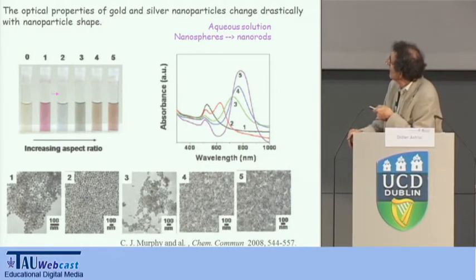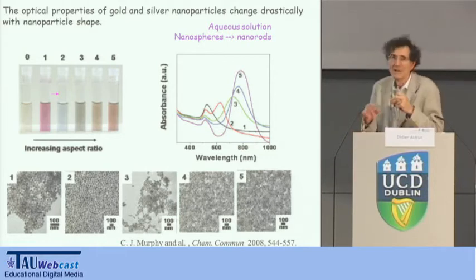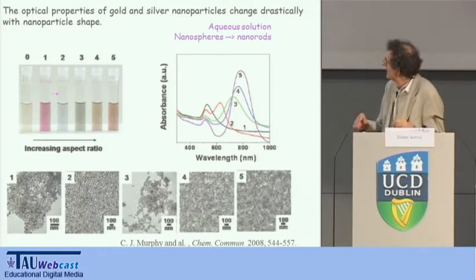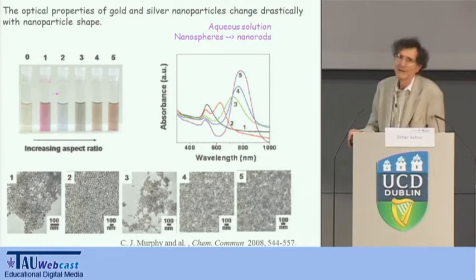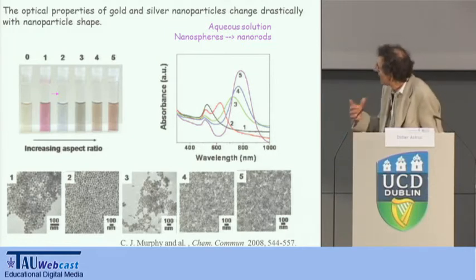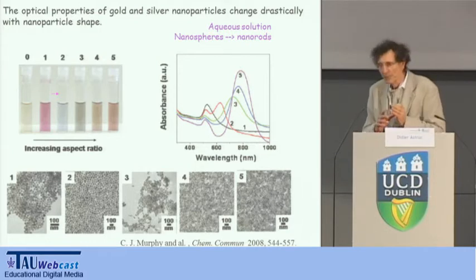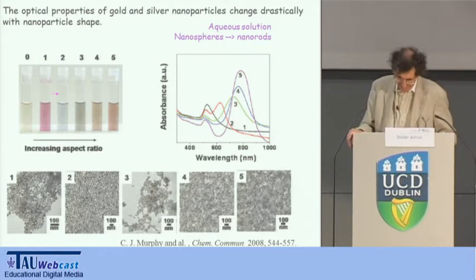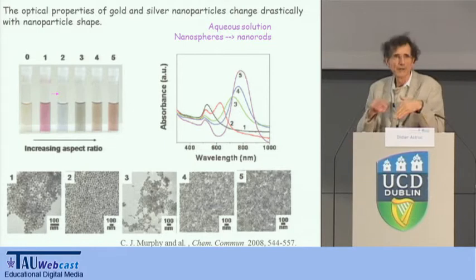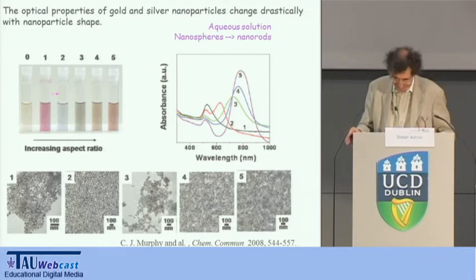And you can see here the variation of the wavelength of the band depending on the shape, from number 1 here, which is in the visible region, which is globular, to number 5, which has a large ratio between the length and the width. So when you have these dots, you can move the absorption from visible to the infrared, and the infrared region is, of course, more useful in nanomedicine because you can go deeper inside the skin in the case of cancer, up to almost 1 centimeter depth inside.